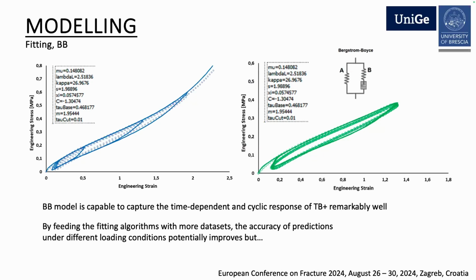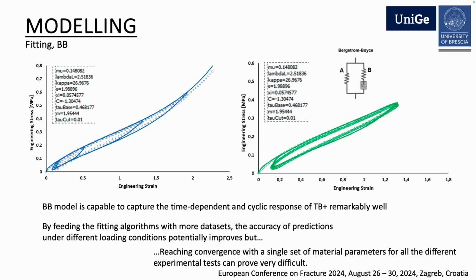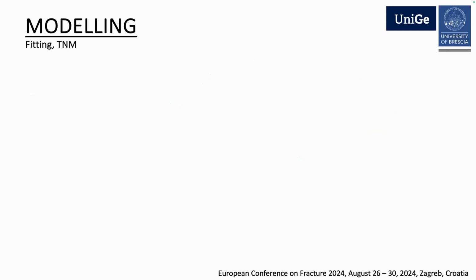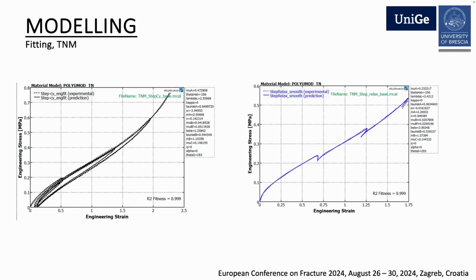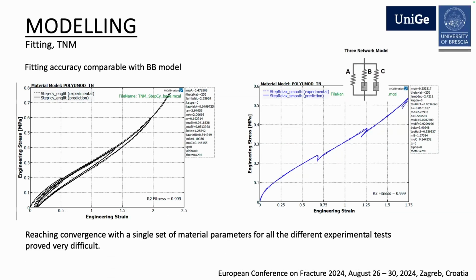So in general, what we found is that in principle, the more different types of data sets you provide to your fitting algorithm, the more potentially accurate your prediction can be, but it may be difficult to reach convergence on a single set of material parameters. And one example is this prediction. This is for the three network model. In this case, you can see that the prediction of the cyclic response or of the step stress relaxation is, I would say, excellent, but the material parameters that we use are different. So in this case, we're not able to find a unique solution.